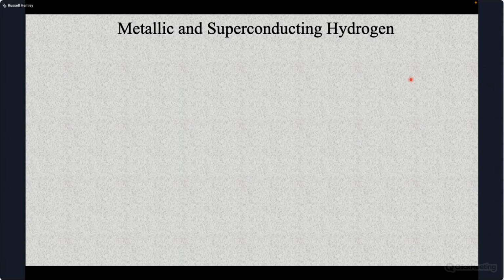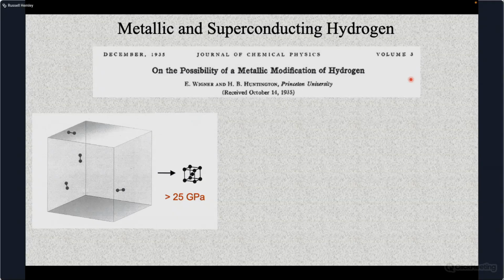Our focus in this field in the last few years has been mainly on hydrogen-rich systems, and this dates back to this paper that I alluded to, by Wigner and Huntington, where in 1935 they predicted that at some high pressure condition, and they set this as a lower bound, above some 25 GPa or 250 kilobars, you would destroy the molecular bonds, as I pointed out in an earlier slide, and form some kind of dense structure, a plasma state,